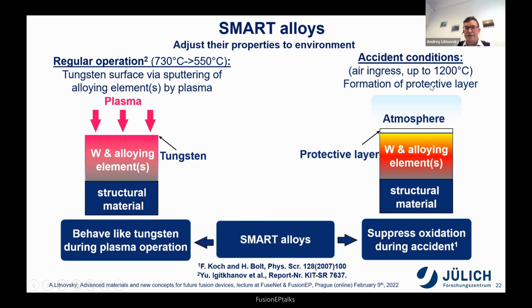During the accident conditions, the alloying elements remaining in the bulk will diffuse to the surface of the tungsten and create their own oxides, because they are more chemically active for oxide formation, and this oxide will protect the tungsten. Now the roles are changed. The alloying elements are preventing tungsten from oxidation.